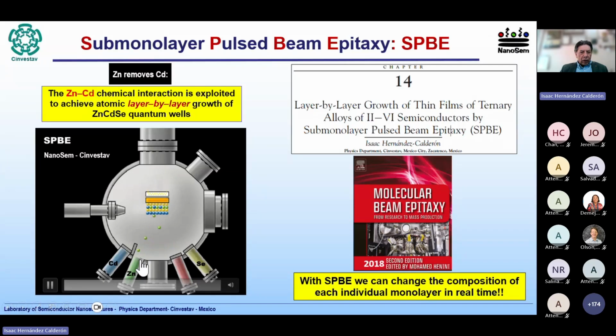And now we open the zinc shutter, and the zinc atoms remove the cadmium atoms. Depending on the time that we open the zinc shutter, we will produce a specific proportion of zinc and cadmium atoms. So this technique allows us to grow in a layer by layer mode ternary quantum wells. We have used this for the production of many different heterostructures. The types of the growth process can be found here.